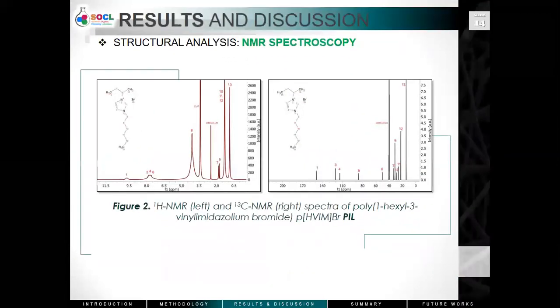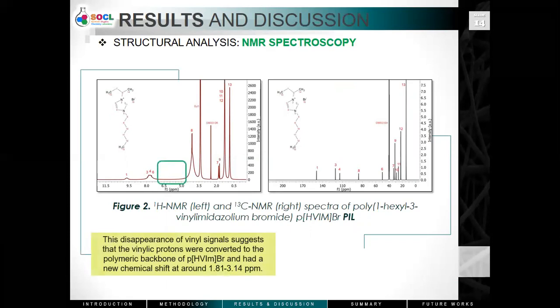Similarly, the proton spectrum of the polyionic liquid confirmed its polymerization, as depicted by the broadening of the signals typical for polymers. In addition, the two doublet peaks at around 5 to 6 ppm of the IL disappeared. This disappearance of vinyl signals suggests that the vinylic protons were converted to the polymeric backbone of the polyionic liquid and had a new chemical shift at around 1.81 to 3.14 ppm.